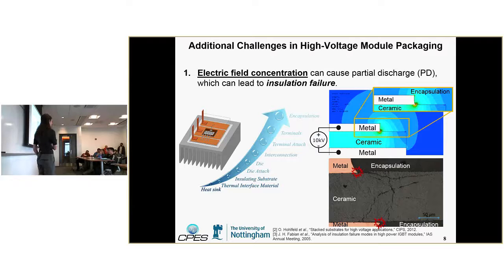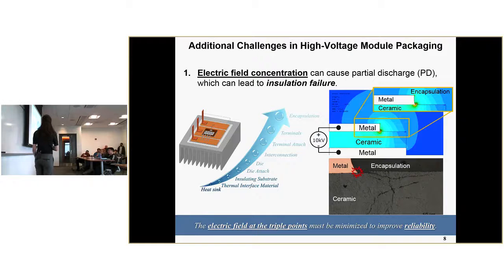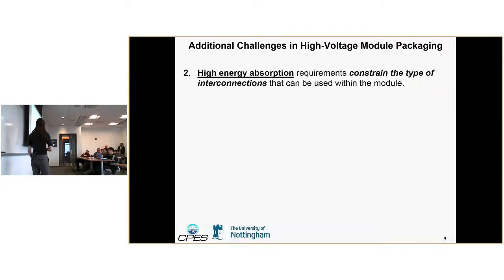So then that completely destroys the isolation from your heatsink, and now your module and your whole system could be damaged. So it's really essential that in these high voltage modules, especially if you want to achieve high density, you need to make sure that the electric field at these triple points is well controlled.